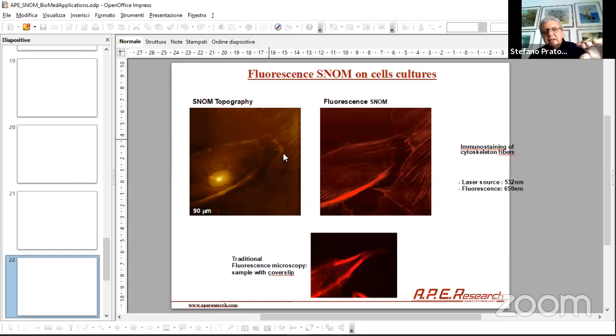This is the image that you can get with the confocal microscopy. This cell was treated with some fluorescence dye, and it's possible to do the fluorescence mapping. So the fluorescence mapping is a slice of a cell. This is what you get. You have some very bright parts here and some, let's say, less bright parts here. And this is the image that we obtained with the SNOM.